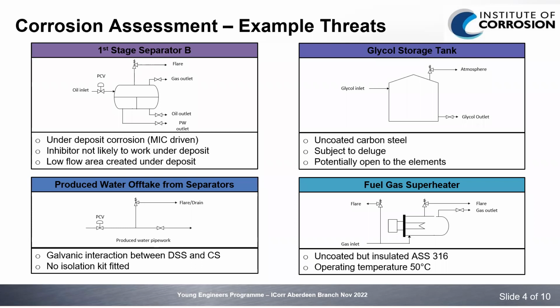And this next one, this one's actually quite a key threat that we've identified. It's the fuel gas superheater. So it's working above 50 degrees and it's not coated, but it is insulated. So if the insulation is wet, then there's going to be a high risk of stress corrosion cracking underneath there.